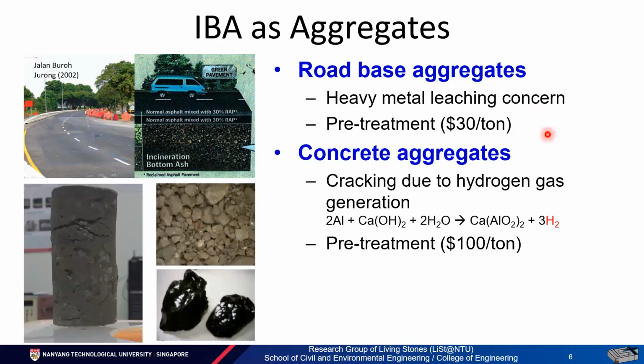Another proposed use of IBA is as concrete aggregate. However, it has been observed in lab experiments that when IBA is used as concrete aggregates, it often reacts with the surrounding cement and generates hydrogen gases, which causes cracking. One way to overcome that is high temperature vitrification, converting IBA into a stabilized glassy material. However, this treatment is associated with high temperature and high energy, which makes the IBA cost increase to $100 per ton.